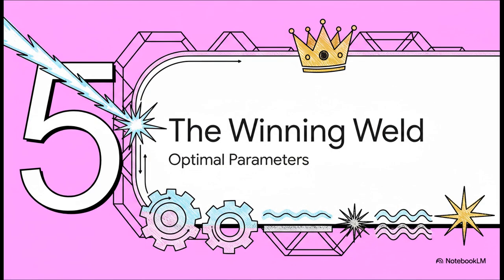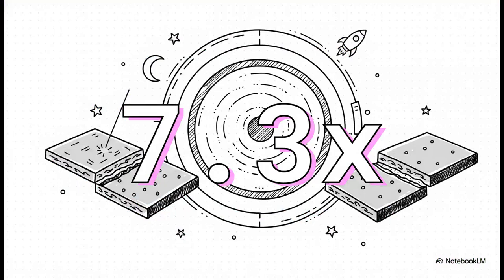All right, Section 5, the winning weld. Okay, the data is all in, and we are finally ready to crown the ultimate champion of this metallurgical showdown. And honestly, if you needed one final absolute slam dunk piece of evidence, just look at this number, 7.3. See, the researchers put both of these welded plates through an X-ray computed tomography scan. Think of it like a 3D medical CT scan, but for solid metals. They were looking for microscopic pores hiding deep inside the fusion zone. And what did they find?